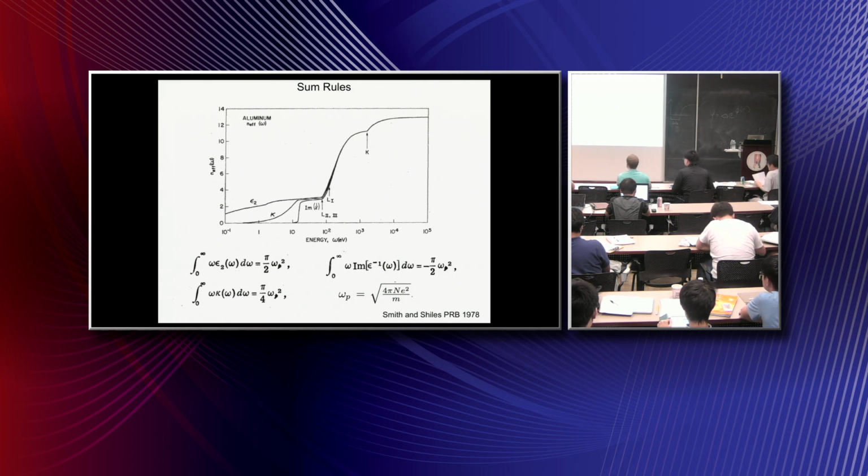Okay, above all transitions, let's say Q equals 0. If I make some particular solid and I have low energy, I have energy levels right near the Fermi energy, and I can excite those with milli-eV or 1 eV energies. I have orbitals which are lower down, and I can pull those up, et cetera, but eventually, if I go to high enough frequencies, I've essentially exhausted all possible electronic transitions, and I would expect for omega much, much greater than omega c, that epsilon 2 equals 0.